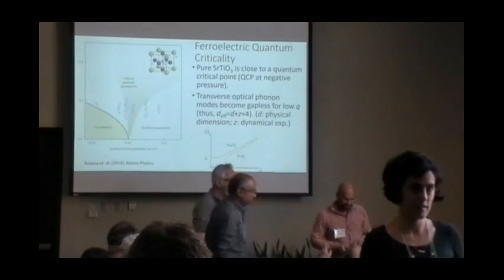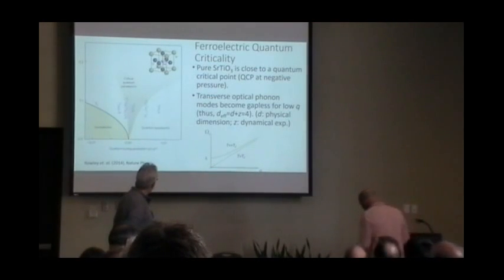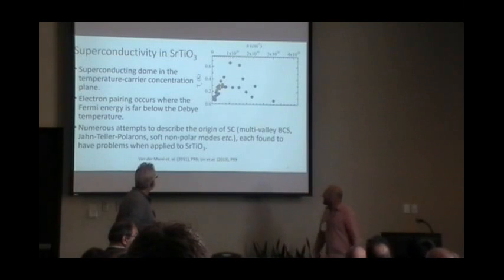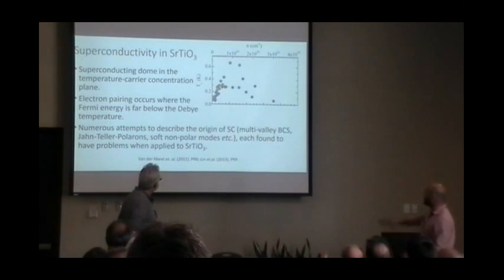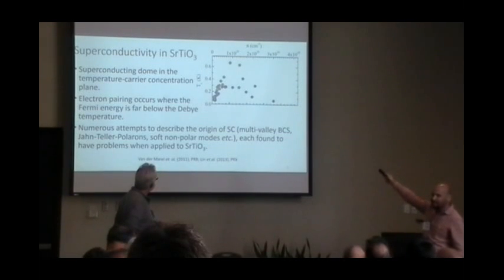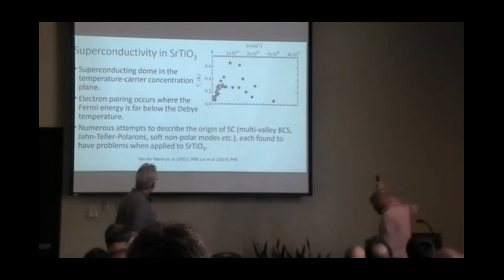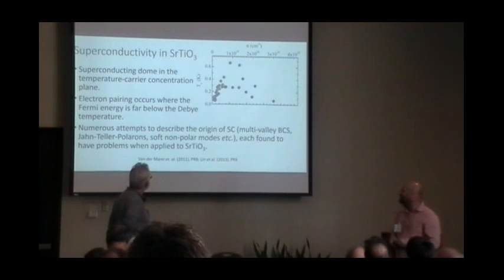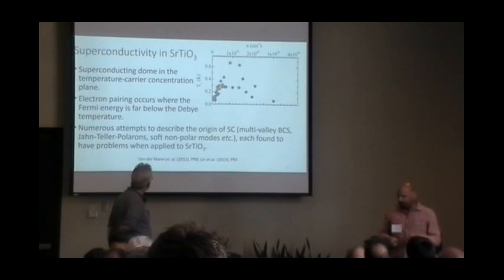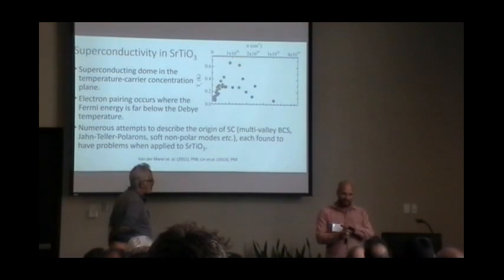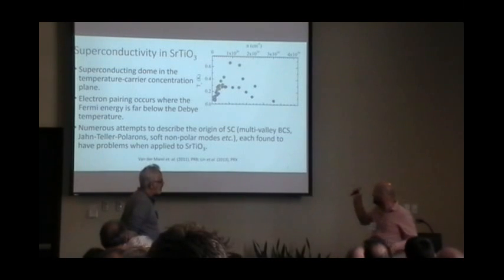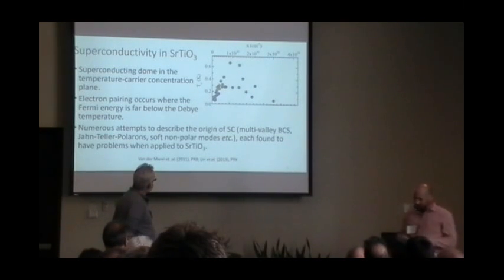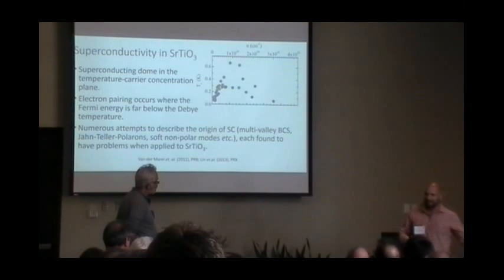Thanks, Sergey. I come back to these two curves. Apparently they have the same slope at the beginning, and then the maximum is different. Well, I wouldn't say that this is necessarily true, because both scales are linear now. If you plotted them logarithmically, it might look a bit different. One of the huge difficulties of the experiment was that we found, although we haven't proven it yet, that there seems to be a phase segregation, at least to the surface. So you kind of have clustering of the dopants. I don't know how it is with the oxygen substitution because we didn't try that, but it's very likely that this will create strong effects in the TC.